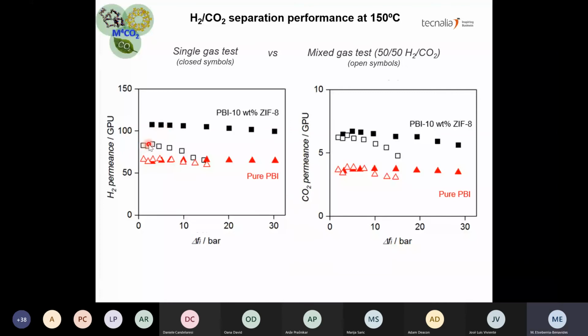It remained constant at low pressure, but then as the pressure increases, it falls to the same value as the pure PBI hollow fiber. A similar tendency was observed for the CO2. So at the beginning, it remained constant, and then it falls a bit as the pressure increases. This phenomenon was attributed to competitive sorption between hydrogen and CO2 molecules.